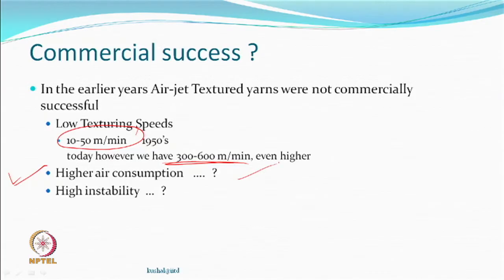How can you do any kind of mechanical process so fast? This process may appear very simple, but it is not, because you still want a useful product. Higher air consumption means cost. There is also a process property called instability — you have generated some loops and crinkles, you put them under stress, and they open. If you run at high speed, you are just not able to accomplish opening of filaments, loop formation, and entanglement all within that 0.005-second time frame.